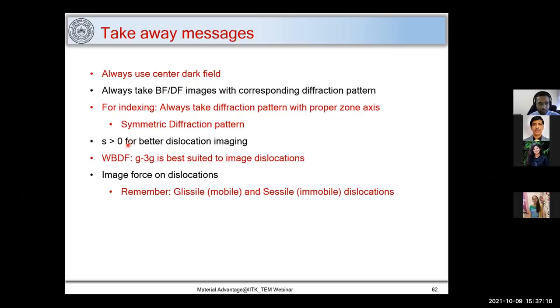For dislocation imaging, the deviation parameter must be greater than 0, or positive. The weak beam dark field condition, the g-3g condition, is the best suited for any dislocation imaging. And last but not least, whatever dislocations you are seeing, some may be glissile, and thus you have to consider the image force acting on them, and some may be sessile. So always make sure what kind of dislocations you are looking at. It is very important to find the Burgers vector of a dislocation when you are doing dislocation analysis. And with this, I will stop here.